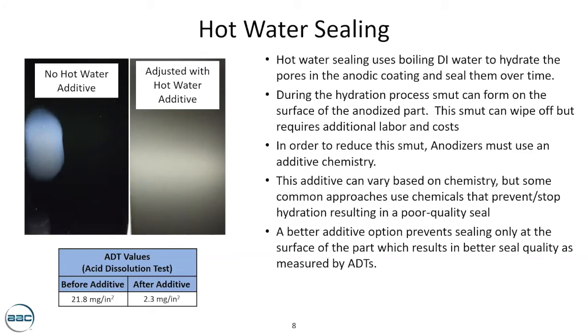So what you'll see here in the ADT values is the part on the left, before we made an additive addition, had a much higher ADT value than after the additive. It dropped significantly. So there are ways to get good ADTs and use a hot water seal. Some additives are much better than others because they have a targeted approach in how they handle hydration. But that's something to consider when you're doing hot water sealing. If you have to immerse a part in a bath for more than 5 minutes, you're going to need some sort of additive to ensure you don't smut up.